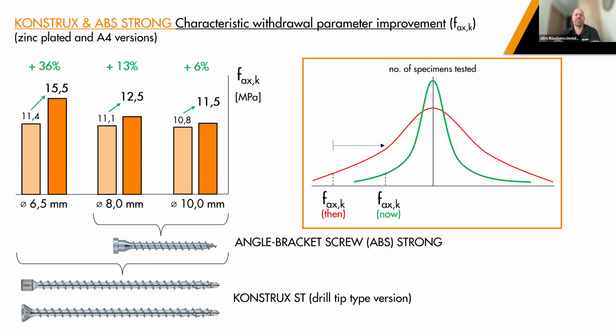And what you see is that none of these additional coatings, and even the zinc itself, is really abrasion proof. That means on long screws, often the first 30% of the insertion channel wears off your coating. So when we talk about excessive corrosion, even submerged partially in water, or H3.2, 3.4, even 5, it should be a stainless steel screw. However, we had many projects here with excellent panels that were also treated in a service class 2 environment where zinc was no issue at all. So for sure, this again depends on increased moisture and how the treatment even then gets washed to the screw.